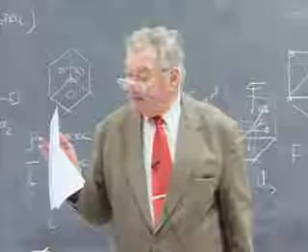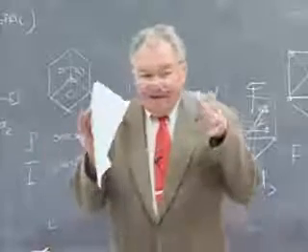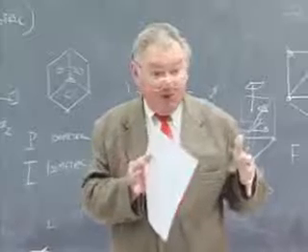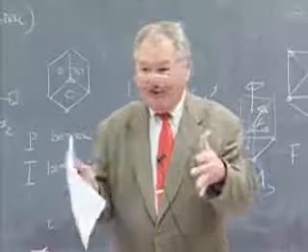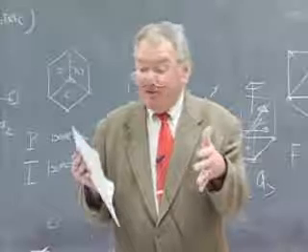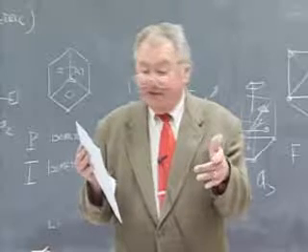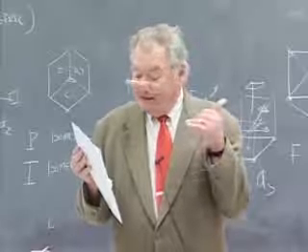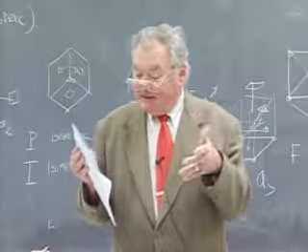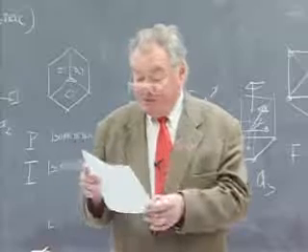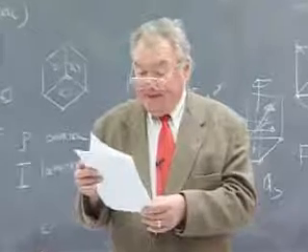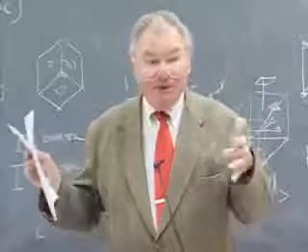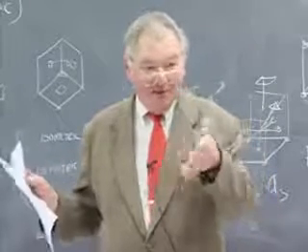Besides that, there is the option of having the symmetry elements of the point group not intersect at a common point, but interleave them, as we did, for example, with the glide planes in P2GG and in some of the other two-dimensional plane groups as well. Then we would do what we also did in 2 dimensions, take the mirror planes and replace them by glide planes, one or both.